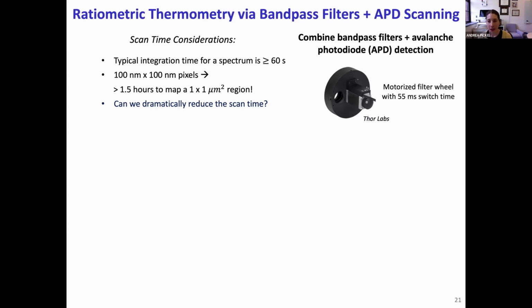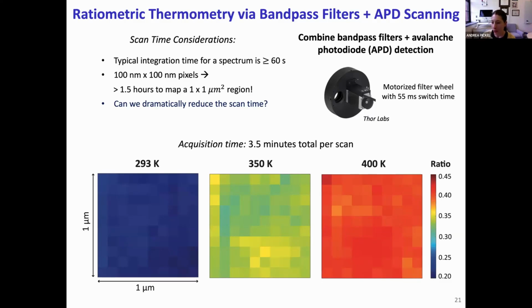And so we wondered if we could instead bring down the scan time by using bandpass filters corresponding to different spectroscopic peaks and using an avalanche photodiode, or APD, to record temperature-dependent ratio maps. We were indeed able to do that, and shown here are ratio maps obtained using APD scans at different uniform temperatures. Because the entire sample is at the same temperature, we expect to record the same ratio at every pixel, and indeed the maps are pretty uniform. And we can also easily tell these different temperatures apart from one another.